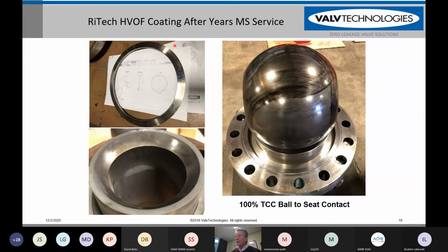Right here you have a Belleville spring, which we utilize both in the stem journal packing as well as the seating area to have what we call live loaded seats. You can see that the seat right here with the tungsten carbide coating is in perfect condition. Also with the ball, there's a slight amount of black oil on here, but no scratching of the ball at all. Interestingly enough, you can actually see, if you look, there's an indentation here of the oil where you can see the contact area between the ball and the seat.